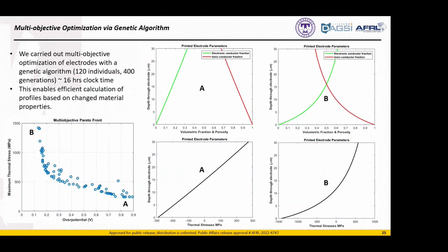So once we have this included, now we can do multi-objective optimization on an electrode, and we can find a grading profile which will both minimize the overpotential or our power losses and minimize the thermal stresses that are induced in the cell as well. So here you see just a linear profile is going to give you the minimized absolute thermal stress, and then a profile like B is going to induce a really high degree of thermal stress but have a lot better electrochemical performance.